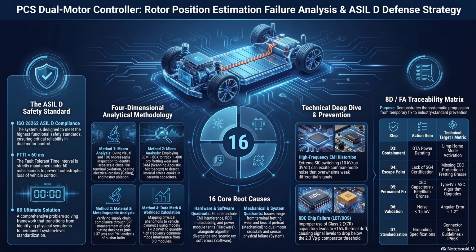Exactly. And under heavy acceleration, hundreds of amps are flowing through that inadequate joint. The reduced contact area means high electrical resistance. Which triggers I squared R thermal runaway. Yeah, the joint generates massive heat, which increases the resistance further, which generates even more heat until the bus bar physically melts and severs the phase connection. All because they missed a chemical dip on a single bolt. The physical saboteurs in these systems are just relentless. They really are. But moving into Section 3 of your provided research, we encounter a completely different class of failure modes. We leave the realm of mechanical friction and parasitic inductance entirely and enter the realm of pure data corruption.